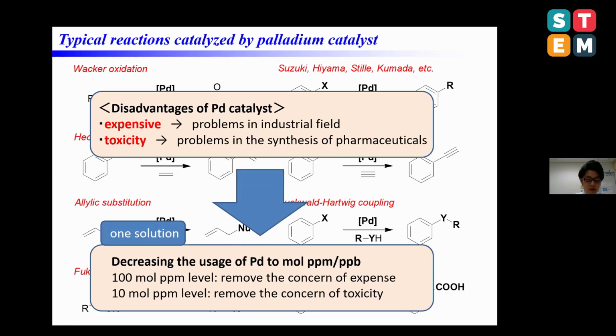Therefore, one solution of these drawbacks is decreasing the catalyst loading. Reaching a level of 100 ppm will remove the price of the catalyst from the reaction. And reaching 10 ppm would remove the concern of toxicity, the catalyst loading used for the reaction being already at the same level as the requirement for palladium impurities in medicines.